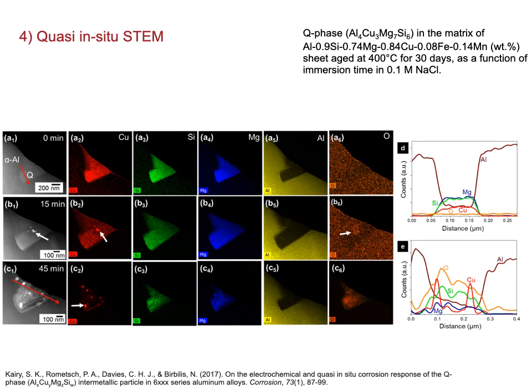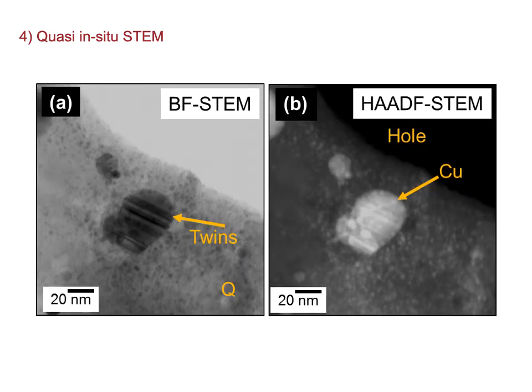All right, moving on to quasi-in situ STEM, which has really been driven hard in the field of corrosion by Kairy. Here we see an example that reveals that Q phase, which is an aluminium, copper, magnesium, silicon precipitate in 6000 series alloys, which are useful in architectural and automotive and transport applications, also de-alloys. Perhaps not surprise, surprise at this point. What's even more interesting is that copper also redeposits back onto the surface of Q phase itself, and does so in a manner that shows so-called growth twins, which are often seen in electrodeposition of copper thin films. So there's clearly much happening here that's yet to be fully unraveled.